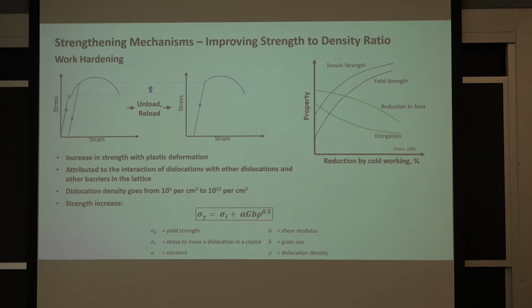So there's a lot of dislocations in a material. You'd be surprised. From what I've heard, in a cubic centimeter of a piece of aluminum, there may be somewhere between 10 to the 5th and 10 to the 12th dislocations. That's a lot of dislocations in there. I've heard that if you added up the length of line of these dislocations in a cubic centimeter of aluminum, that line can be as long as 50,000 kilometers. So it gives you an idea of how small atoms really are compared to a cubic centimeter, and how many dislocations can be in there, adding up all that line, and how much defect volume there is inside such a small volume of material.